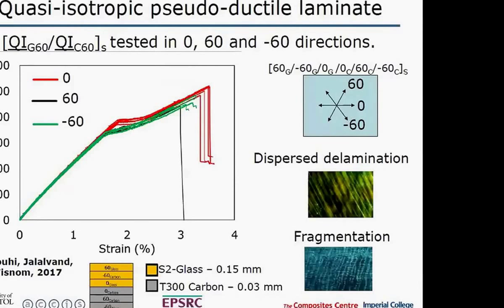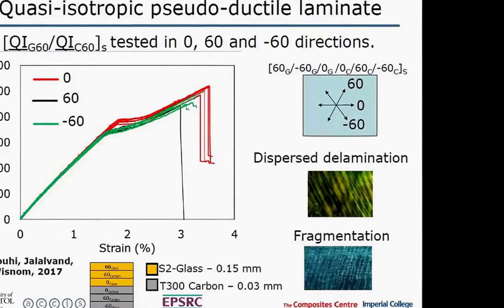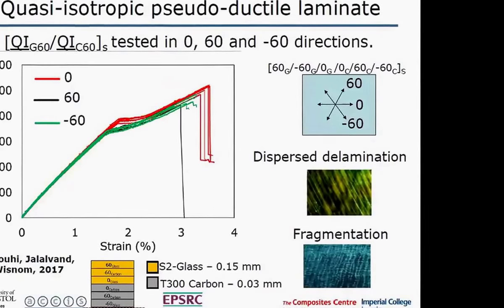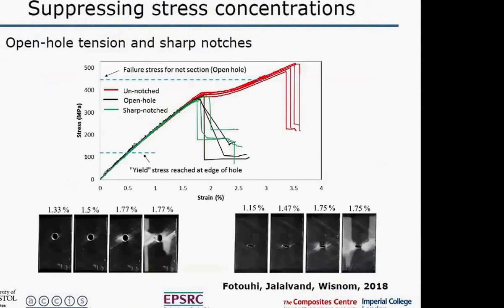So we can get a quasi-isotropic response with pseudo-ductility in any direction, and indeed off-axis we also get a pseudo-ductile response as well. And we get the same sort of failure mechanisms that we see in the UD, with dispersed delamination and fragmentation occurring in the carbon plies.